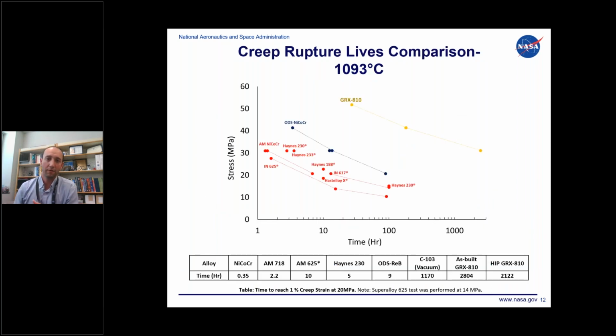So if you look at an overview of creep rupture lives compared to GRX-810 on this log scale map with stress on the y-axis, you can see that your more conventional high temperature wrought alloys, 625, 230, 233, are all kind of grouped together where you get a handful of hours at these low stresses, whereas with GRX-810 you can either significantly increase the stress of an application and get similar lives, or get orders of magnitude longer life at the same environment.